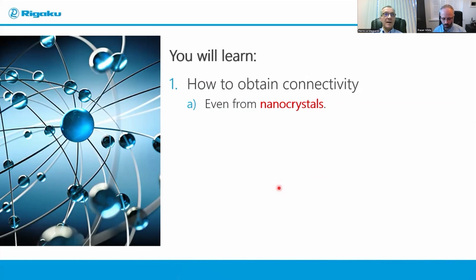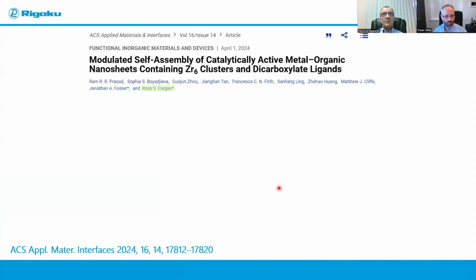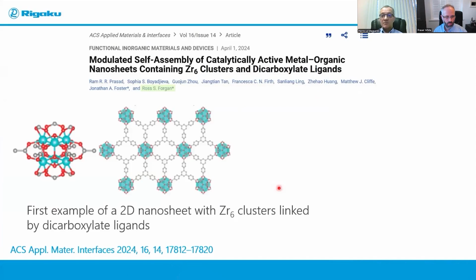If you have a powder and the powder is crystalline, then electron diffraction may save the day. And that's what happened here in this project. This is a paper that Ross's group published last year, and they showed that by a careful modulation of the self-assembly of the clusters, here the zirconium-6 cluster, with the linkers, along with careful control of the exfoliation conditions, this allowed Ross's group to isolate the first 2D nanosheet built from a zirconium-6 cluster. Okay? So this is not a 3D MOF, this is a 2D MOF.